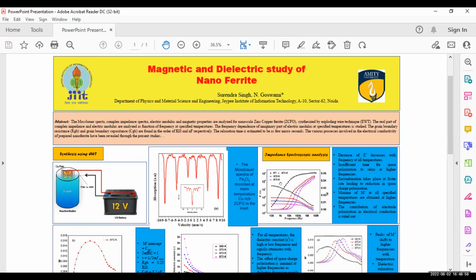The next graph is the modulus graph of the electrical modulus at 5 different temperatures, and we could see the peak of these graphs shifts to higher frequency. This shows that the relaxation process is also thermally activated, and also that conduction in the material is motivated by the hopping of the charge carriers.